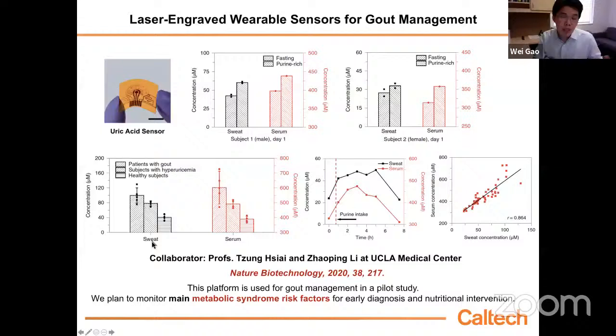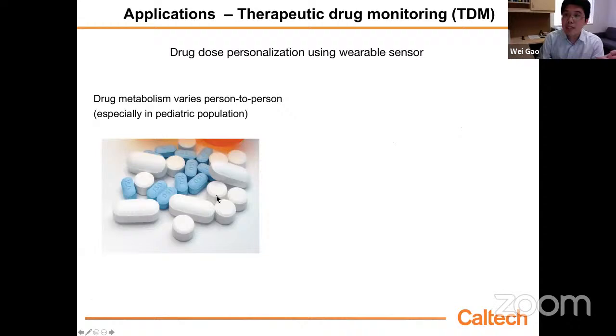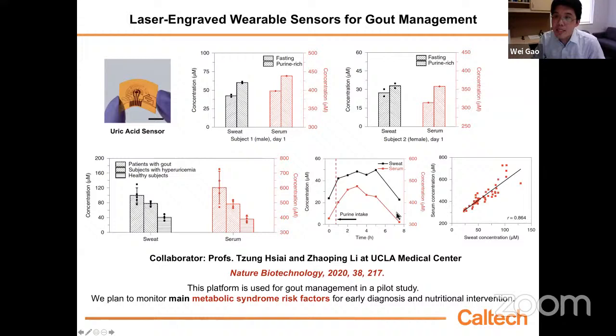And we actually recruited patients with gout, subjects with hyperuricemia, and healthy subjects, and compared them. You see, for the patients, sweat and serum data are both much higher compared to healthy people. And from here, we tracked one subject over 7 hours for both sweat and serum. We found that sweat followed closely to the serum uric acid level. And if we plot the correlation together, you see we get a correlation factor around 0.864. It's pretty high already, we think, because this is without interpersonal calibration.